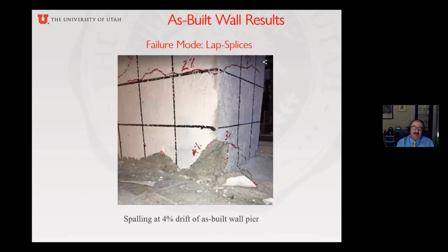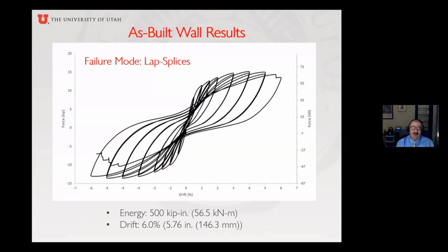So here's the first test. We failed the lap splices here at about 4% drift. And as we expected, the load was not very high. It was about 15 kip. Drift wasn't too bad, actually. It went a little bit further than what we thought, but it's definitely not performing, as I will show you, as well as the modern code detail wall.